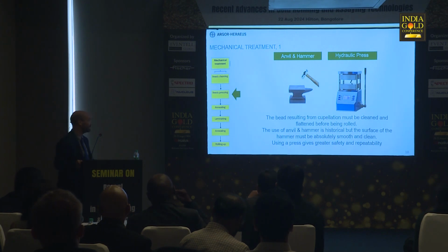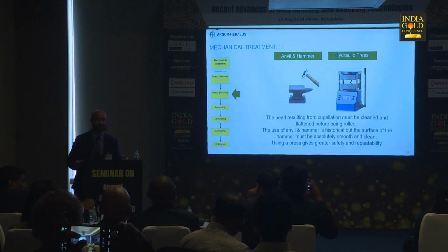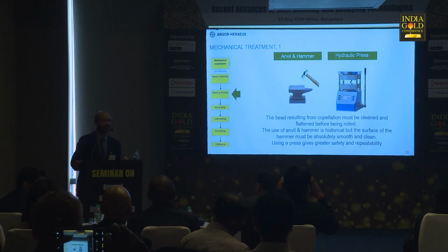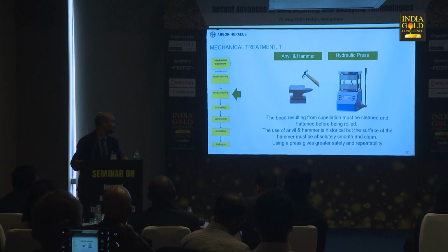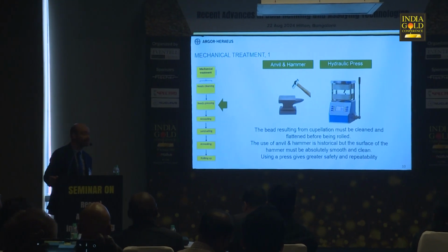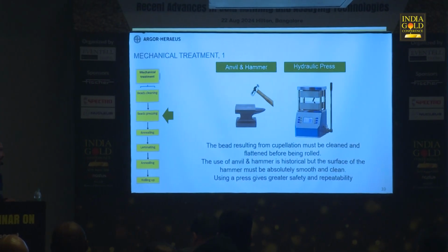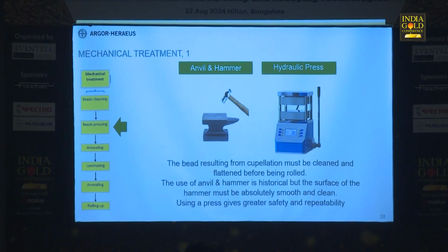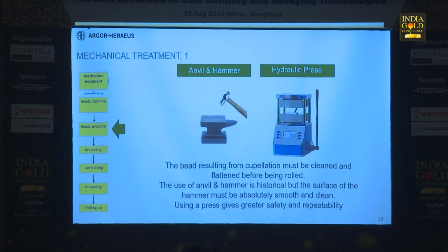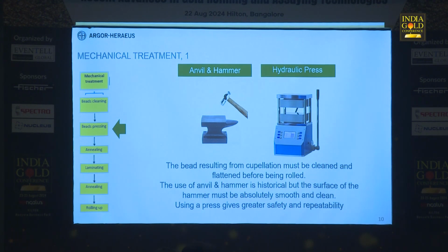Next step is the mechanical treatment. This is a very important part of the process. The first step is the cleaning of the beads coming from the cupellation. The second step is this one. We must flatten the samples before laminating and rolling them up. Historically, we have done it using an anvil and hammer. It's a good way to do it. It's cheap and fast, for sure. But you must be sure that your anvil or your hammer has a good surface. That means you need a stainless steel hammer and a very, very flat and smooth surface. A human error can be made. That means you have the beads, someone pressing with the hammer.